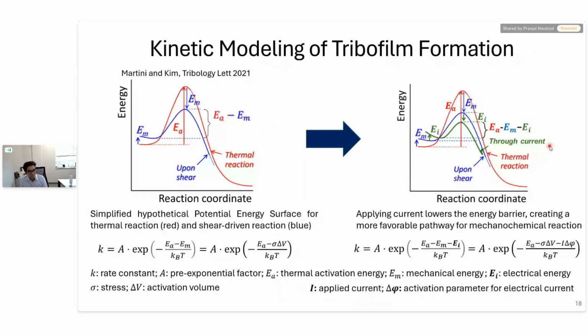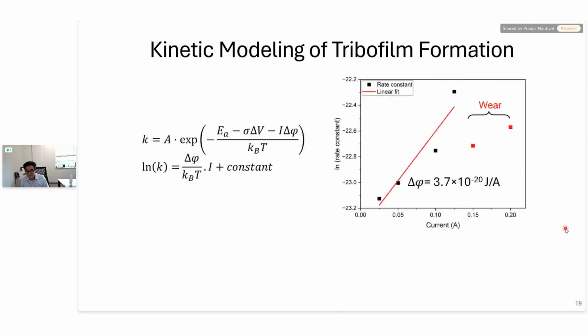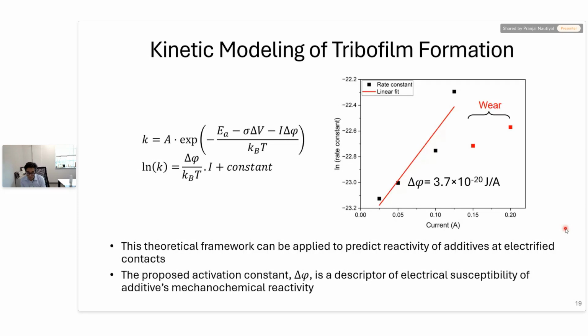We can further decompose this EI parameter as a product of the applied current I and a new activation parameter, delta phi. We take this inspiration from sigma delta V, which captures the effect of stress. We extend that concept to capture the effect of applied current on mechanochemical reactions. And so we can apply this framework to our experimental results that I showed you 2 slides ago, and we can get the value of this activation constant, delta phi. We propose that this theoretical framework can help us predict the reactivity of lubricant additives at electrified contacts.